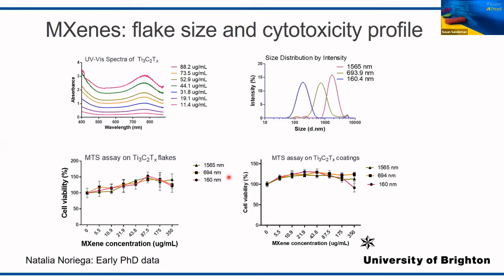Because if you think about the size of cells, cells are made up of nanomachinery effectively. So when you're working with nano-sized materials, you need to think about the interaction of those materials with membrane receptors, with intracellular pathways, and that could be an issue. So Natalia, carefully, you can see the size distribution of materials here, looking at three different flake sizes, and again, looking at cytotoxicity assays over a concentration range up to 350 microgram per mil, and has shown no difference in the cytotoxicity profile of those materials. So it appears that flake size doesn't make a difference to the